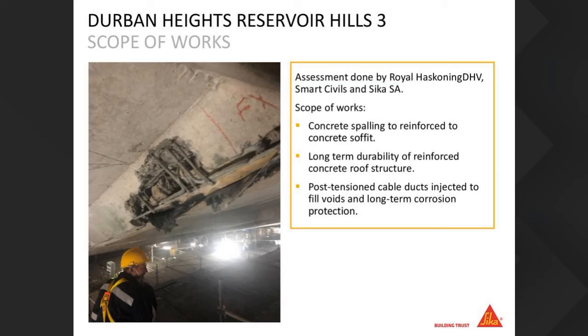And the post-tension cables that were filled back in the day with bitumen mastic were leaking, and over all the years it basically created voids, and there was a big risk of corrosion within the ducting system. So we needed to provide an injectable system that would also offer long-term corrosion protection for the pre-stressed cables.